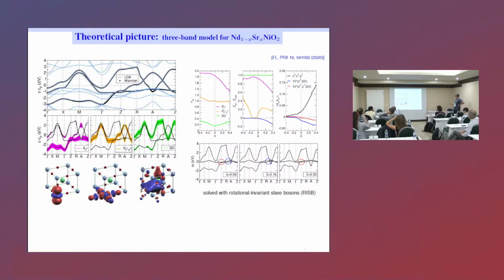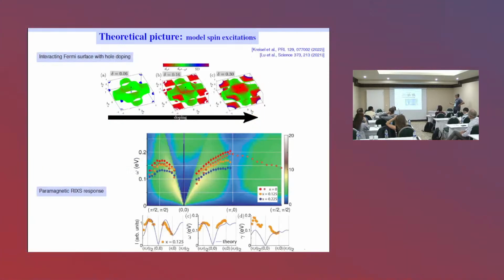Then we teamed up with Andreas Kreisel, and we plugged in this kind of dispersion into his machinery of doing RPA susceptibility, spin fluctuations, and this is a similar curve as Carsten was showing. Here's our comparison. It looks a little bit better, I have to say, at the moment than Carsten's one, but that could be an accident of RPA or whatever. It's of course a bit more simple than what Carsten does, but the agreement, at least again, also on this level is rather fine.